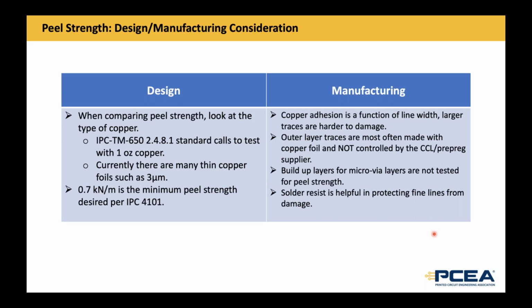The last thing is, in the history of circuit boards, the last bastion of hope for fine lines and spaces is often solder mask, solder resist, because once you coat a circuit, it's very hard to damage. So those are things that you should keep in mind. If you design a circuit that's going to be on the outside of a board, and it's very fine, say 50 to 100 microns, and you don't put solder resist on the surface, it's very easy to damage. That's it.